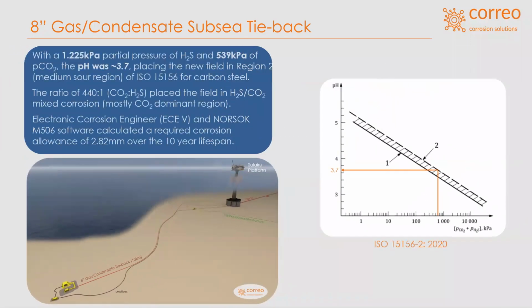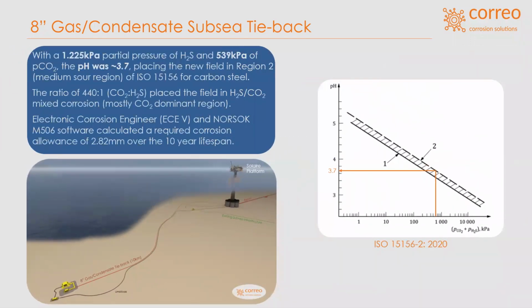So we were given the data that there would be 50 parts per million H2S, as well as 2.2% CO2 content. So with this, we then calculated partial pressures of 1.225 and 539 kilopascals of H2S and CO2 respectively, based on the design pressure of 245 bar.